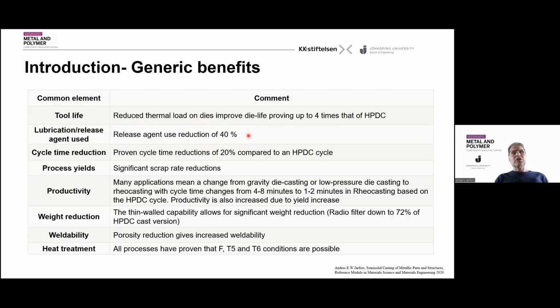Another benefit of reducing the die spray is that cycle time is being reduced because the spray cycle is going down. And that is also a critical element. What has been seen also is that you have significant scrap reduction at the casting station because of the fact that you actually have less porosity and less issues with the release agent. And that means that what we can talk about in terms of productivity, since one of the benefits is that you have to use lower silicon alloys. That means that we're moving into alloys that normally are seen in gravity die casting or low pressure die casting. And that means that we can offer a productivity which is like high pressure die casting, but with alloys and quality which is similar to gravity die casting processes.